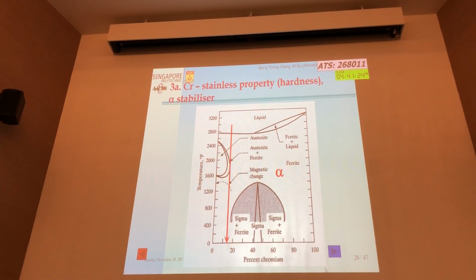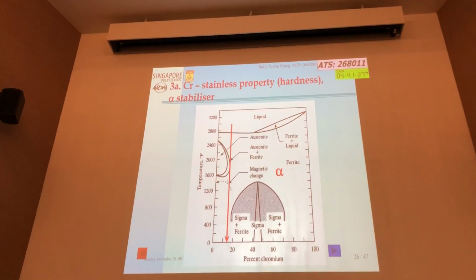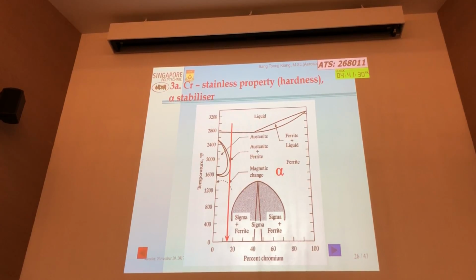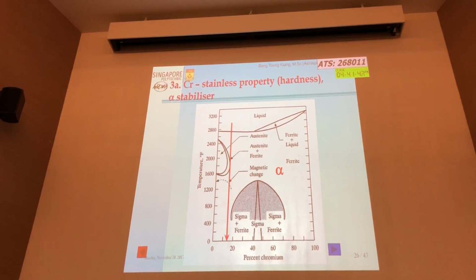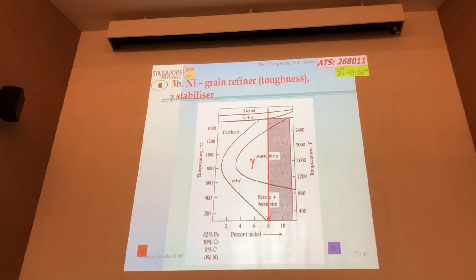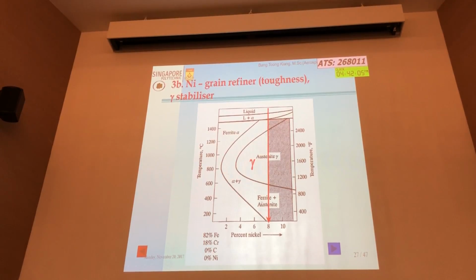That's why I really want you, it's a difficult topic, right? Okay, so you get stainless property, but you produce alpha, you stabilize alpha. It's just an alpha stabilizer, like beta stabilizer in titanium. Now, our aim is not only stainless, we want it to be non-magnetic right now. So we need to make sure that it is stainless and yet it's gamma. But we have no choice, we need stainless chromium. So to counteract this, we add nickel. You see, at least 8% nickel, then you bring the austenite down.